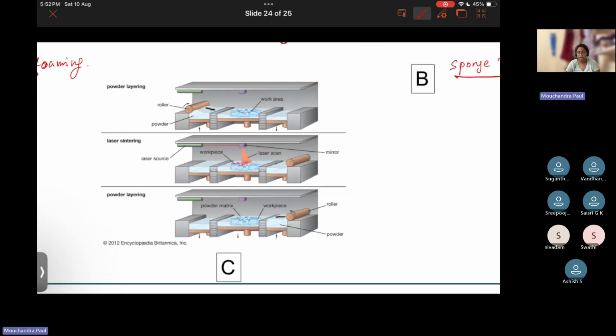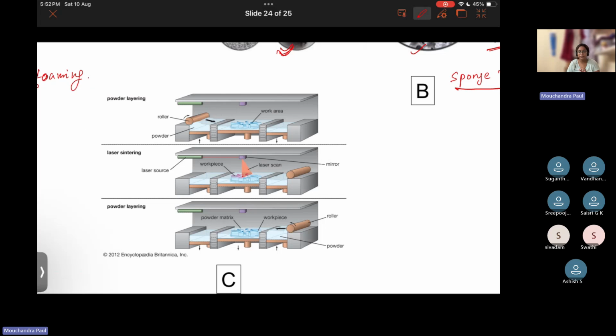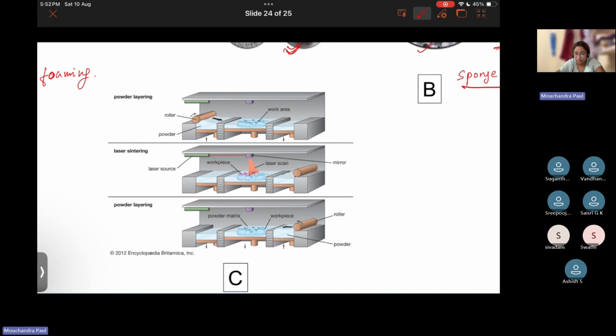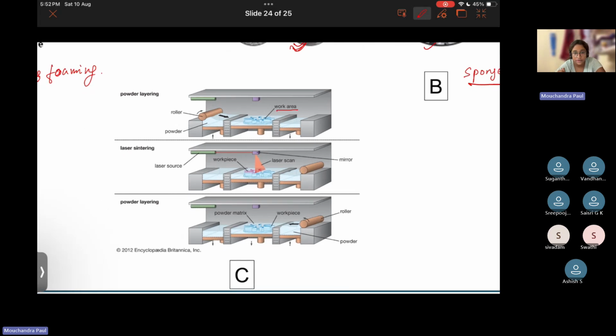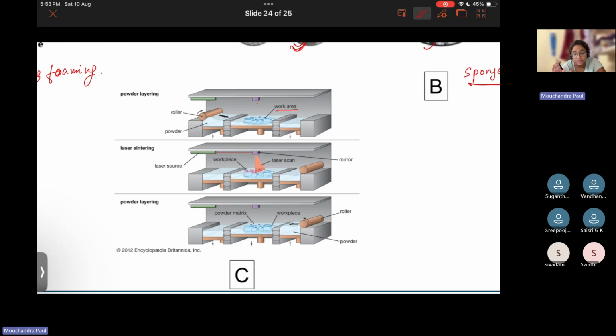This is another method very commonly used for making ceramic based scaffolds. Here, this is your work area, and on top of it there is a laser. First, a roller will create a thin layer of powder over your work area. Then the laser will come from the top. It will sinter the powder particles, cooking them at a very high temperature. A very high power laser is used, and at selective regions the laser is allowed to fall and it causes sintering of the powder particles.